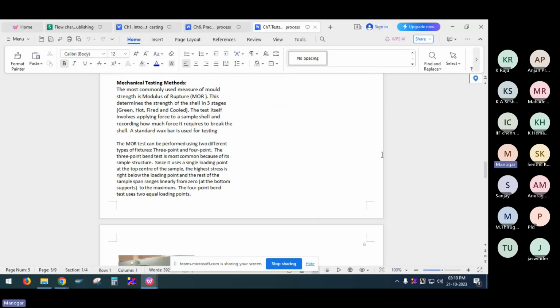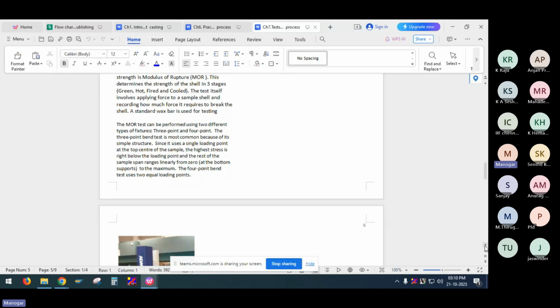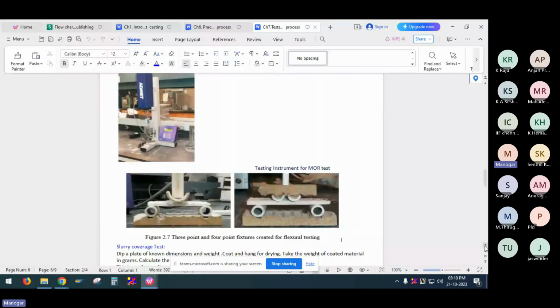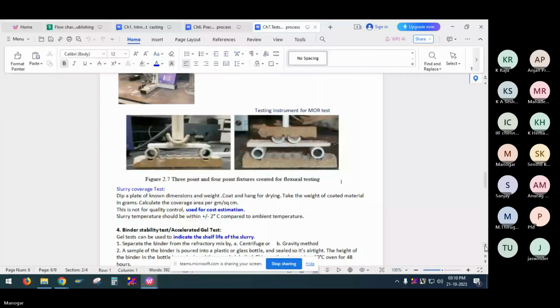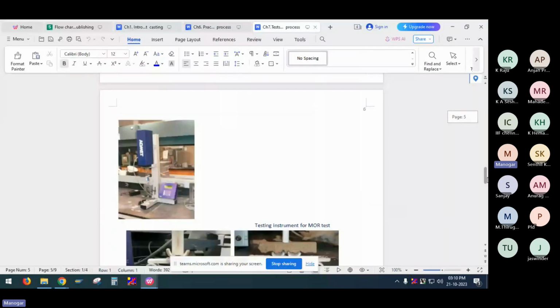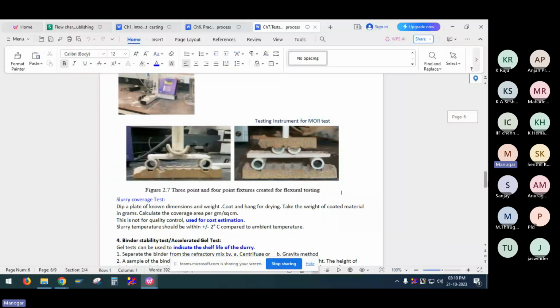The other mechanical test is MOR, modulus of rupture test, that is to test the strength of the shells. These tests also only a few foundries are doing, in export and defense parts. Many of the foundries are not doing the shell test, this mechanical test. They can try to practice this. So they have a 3-point tester and 4-point tester. You can go for 3-point tester, that is sufficient. So with the MOR, we can adjust the number of shell coats or coating thickness like that.